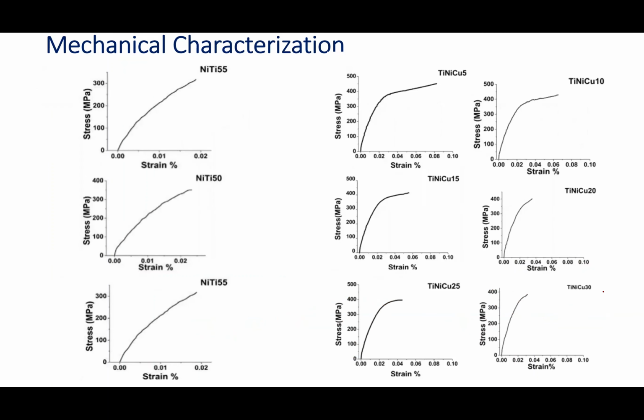Now, in order to study the mechanical properties, we went for a compression test. We did the compression test for both NiTi and TiNiCu based structures, and the samples were prepared as per ASTM standard with dimensions of 5 mm diameter and 10 mm length. At least 3 samples were tested.